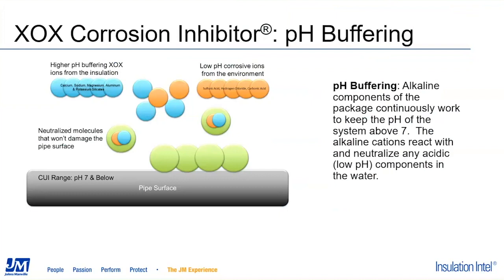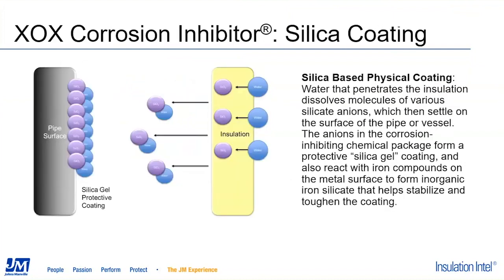So if for some reason you do get the introduction of corrosive ions into the system, typically from the outside environment, so it could be acid rain, or if this is a facility that produces a caustic compound and therefore that compound is creating a caustic atmosphere in the facility, if you get the introduction of those corrosive ions into the insulation system, they are actually going to combine and react with the alkaline ions from the corrosion inhibitor, and those acidic or corrosive ions will get neutralized and the pH will be brought back up to 7 or above, therefore hopefully eliminating the opportunity for that corrosive environment to be present in the insulation system and definitely at the surface of the pipe. So that's the first stage of protection, is by buffering the introduction of any possible acidic elements to the insulation system.